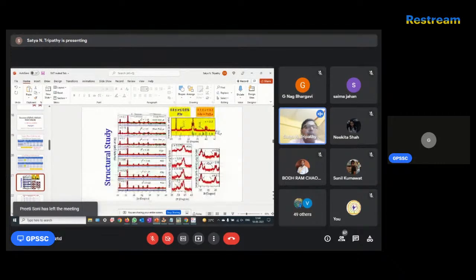I hope this XRD figure is visible to all of you. It tells us that all the XRD patterns up to 0.075 are similar. There is no splitting of the peak, no shoulder of the peak, and not much peak shifting. Only peak broadening will be there because of some chemical pressure or strain effect, because you are introducing some substituents. So some broadening will be there, and double peaks will come to single peaks. These are the effects of strain.